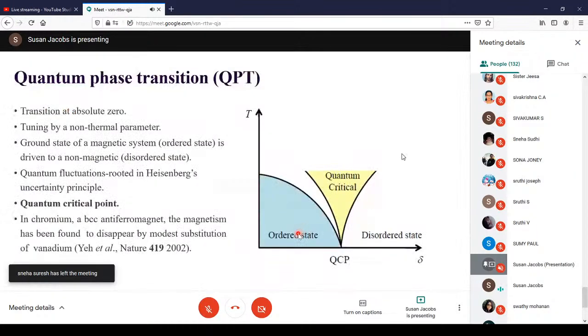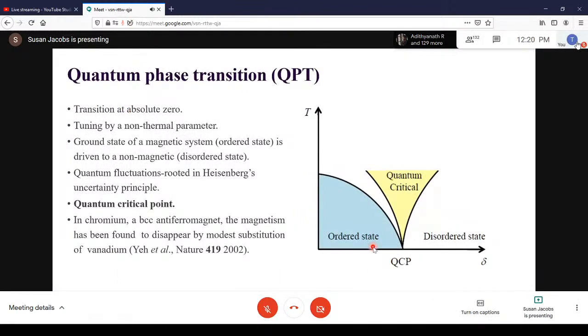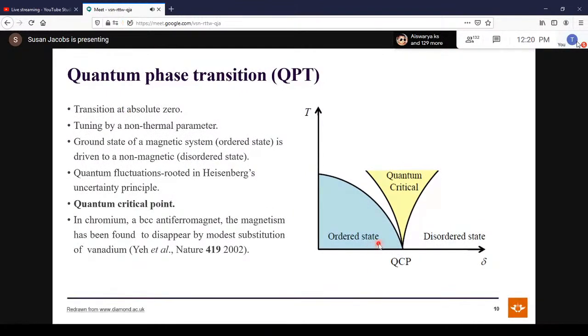The metal is engulfed by quantum fluctuations. The physics is different, and there's a lot of change that happens in the system. Now, although this transition occurs at absolute zero, we can see effects of it at higher temperatures, at about 2 Kelvin. And this was a groundbreaking study reported by Yeh in the year 2002, like I said, that you can drive chromium to a quantum critical point by substituting with vanadium.